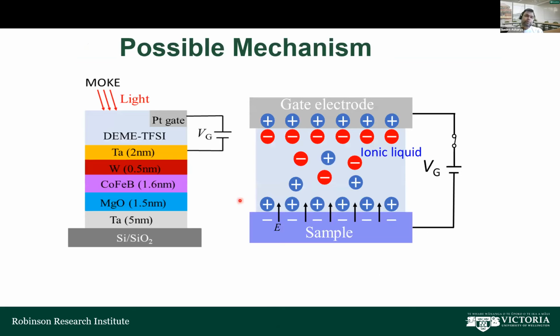So this experiment is really recent, so we have yet to definitely know how this mechanism works, why the anisotropy is changing, but we have some idea. So one possible mechanism is that when we are applying a positive voltage, for example, the negative ions are accumulated at the top of the ionic liquid. As a result, the positive ions are accumulated at the bottom of the ionic liquid. And this can create a very strong electric field, and the oxygen ions can get sucked into the top of the surface.